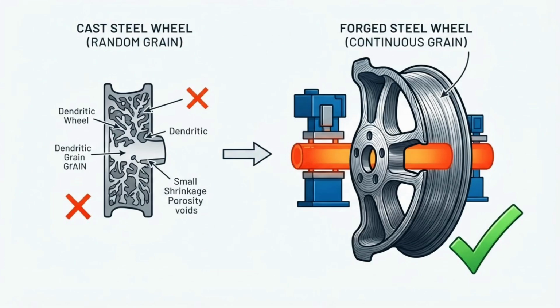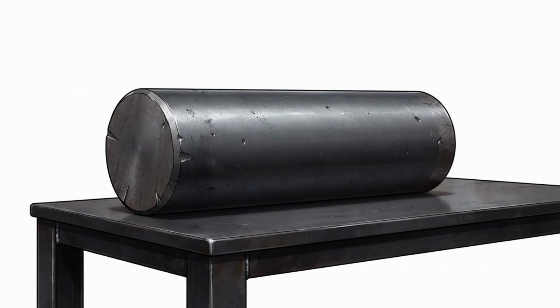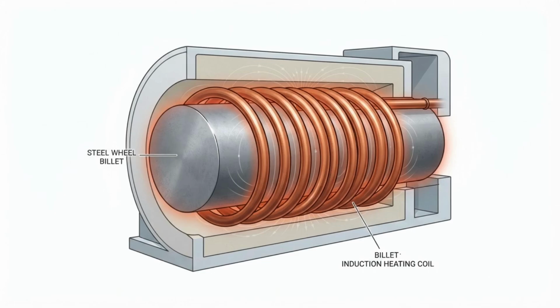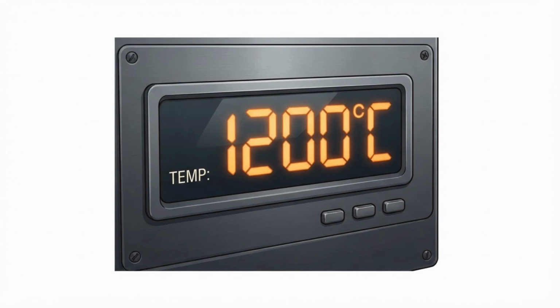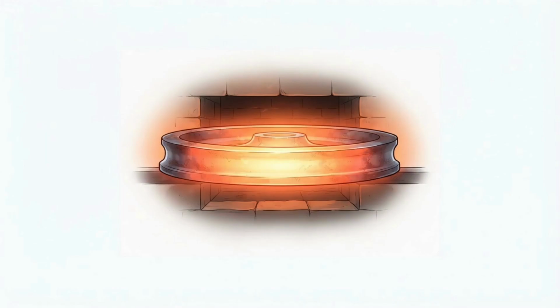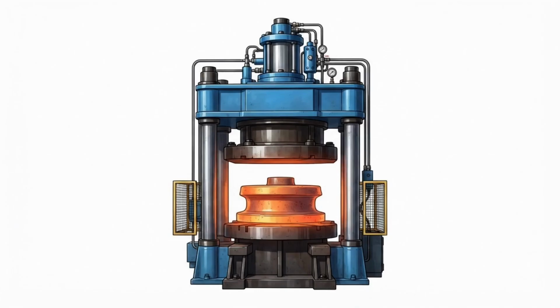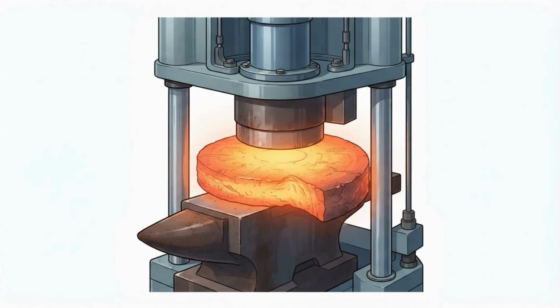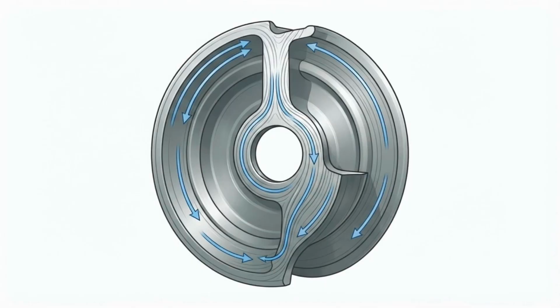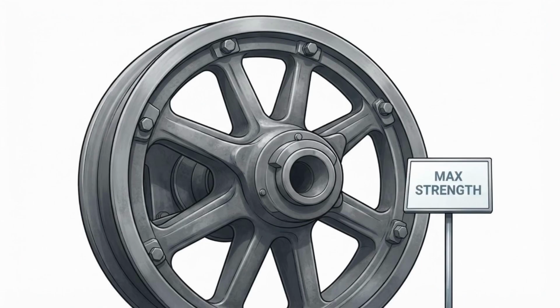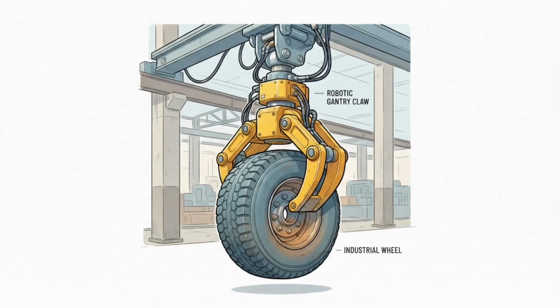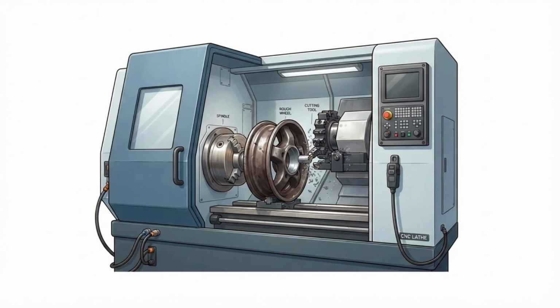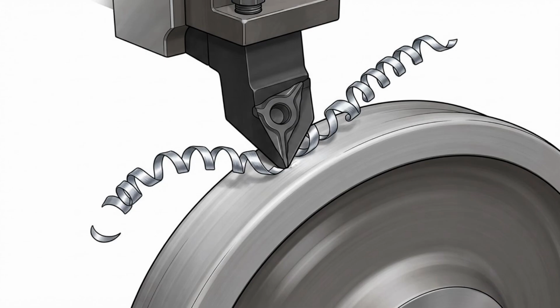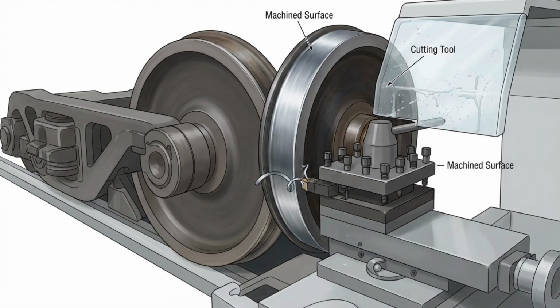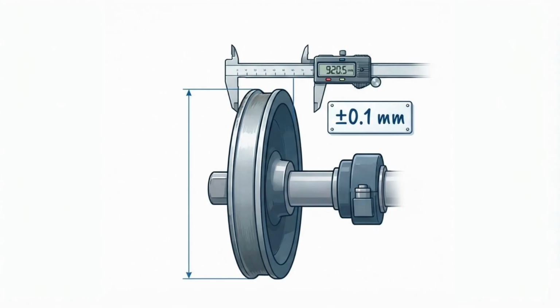Instead, wheels are forged. A solid billet of high-carbon steel is heated in a furnace to over 1200 degrees Celsius until it glows a brilliant translucent orange. A hydraulic press exerting over 10,000 tons of force crushes the glowing billet into a rough wheel shape, aligning the internal grain structure of the steel for maximum strength. The rough wheel is then transferred to heavy-duty CNC lathes, which carefully peel away ribbons of steel to machine the wheel to its precise final dimensions.